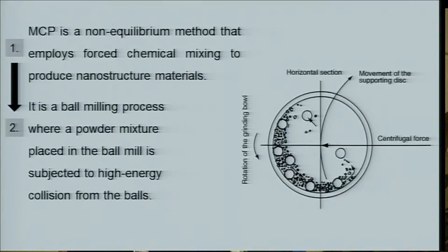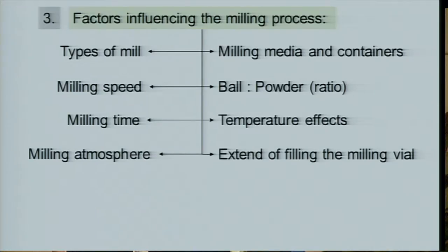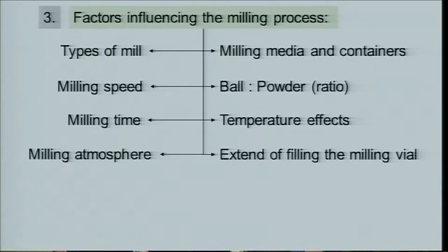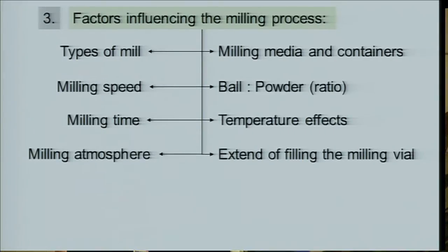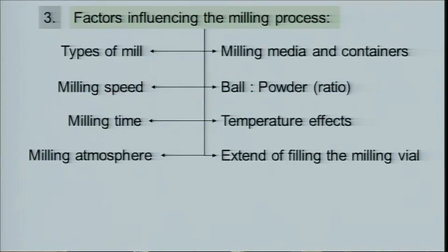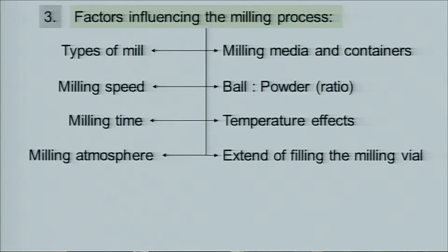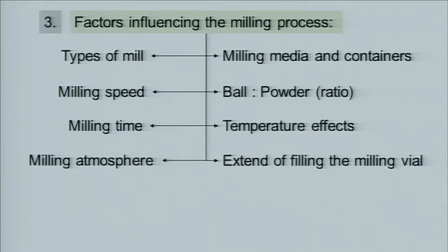Yeah? So basically you have in a container, you put your powder and you put metal balls, very small metal balls, and you roll it. Yeah? And of course, there are several factors that you have to control to get the type of materials that you want. Yeah? So in our case, basically, the variables that we chose were the milling speed and the milling time, those two. Because the atmosphere, the ball powder ratio, the type of mill, everything we kept constant. Yeah?